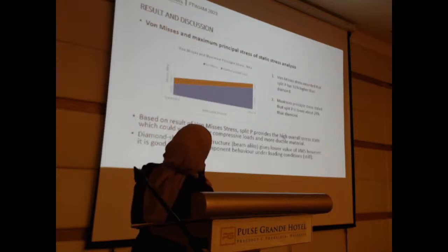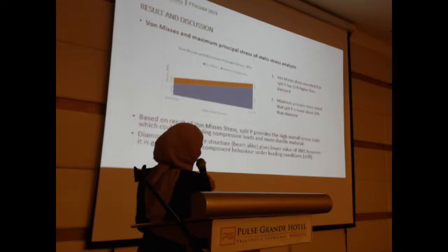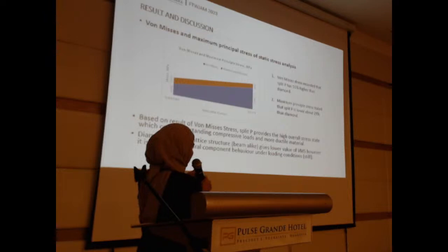Okay, result and discussion from the result that I received from the analysis. Von Mises stress recorded that split P is 55% higher than diamond. However, the maximum principal stress is about 29% lower than diamond. So based on the result of von Mises stress, split P provides a high overall stress state which could withstand compression load, and split P is actually more ductile compared to the diamond.